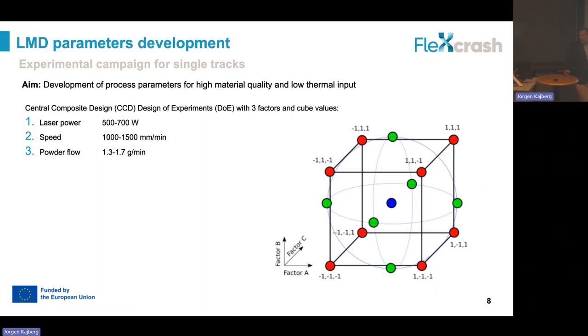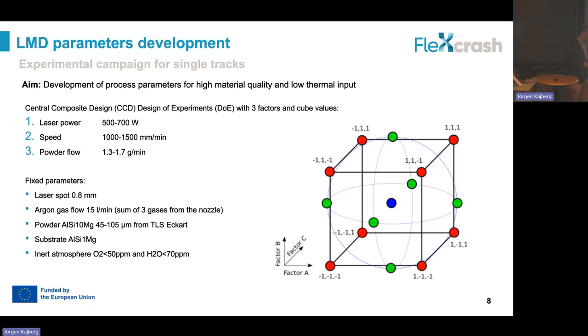So, development of the process parameters. In our technology, as I said before, we have three main parameters because we need to control the amount of material, the amount of energy that we put into the process, and the speed at which we do this. So the three parameters we want to control are laser power, speed of the movement, and the amount of powder that we feed through the nozzles. Then we have other fixed parameters that depend mainly on the system and the material that we're using. As I said before, in the case of aluminum, also for safety reasons, we need to operate under an inert atmosphere with oxygen level below 50 ppm. Otherwise, we risk starting a fire with the aluminum powder.